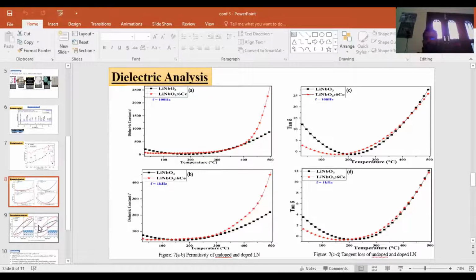Dielectric analysis of my research work. I performed dielectric characterization up to 500 degrees Celsius, and the frequencies I use are 100 hertz and 1 kilohertz. And I found that there is a rapid change in dielectric constant, which is increased for cerium doped lithium niobate compared to pure lithium niobate.